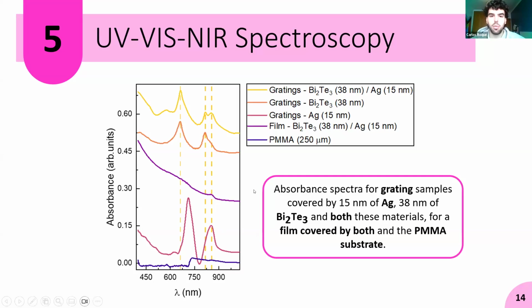Then we observe that when changing from films to gratings, the absorbance is increased. And then you can see that we can match some of the peaks of the gratings with only one of the layers and the gratings with the two layers. So the first two peaks of the gratings with bismuth telluride and silver are from a bismuth telluride contribution because those peaks match. And the last peak comes from a silver contribution since it matches with the only silver grating.